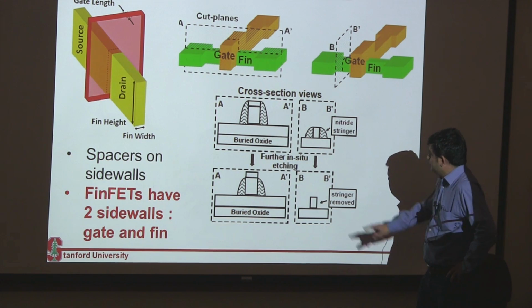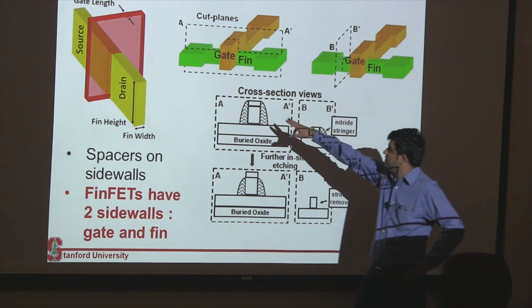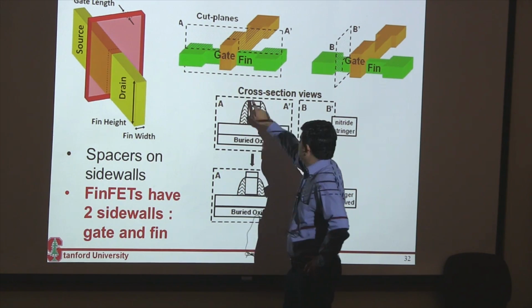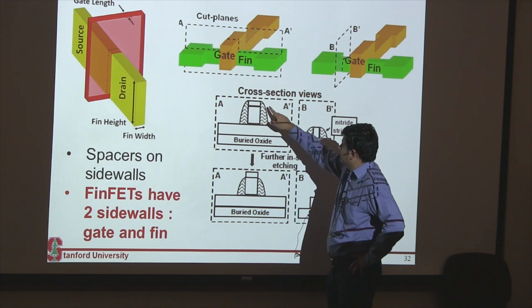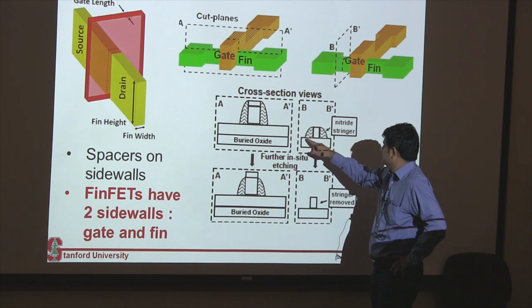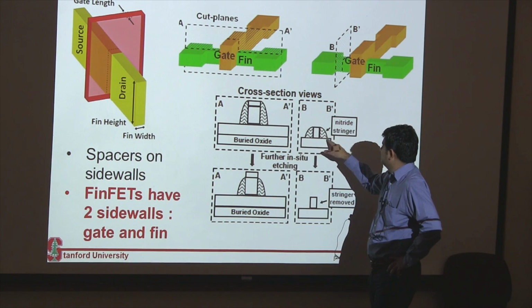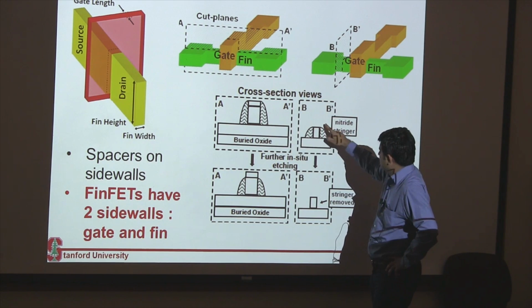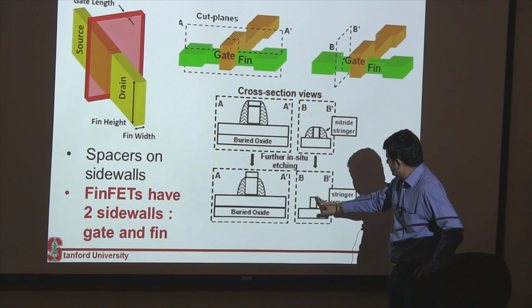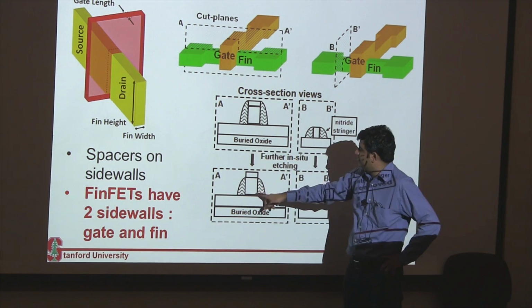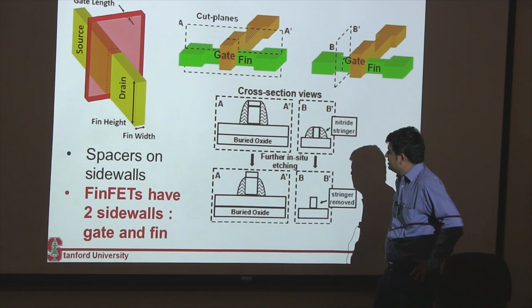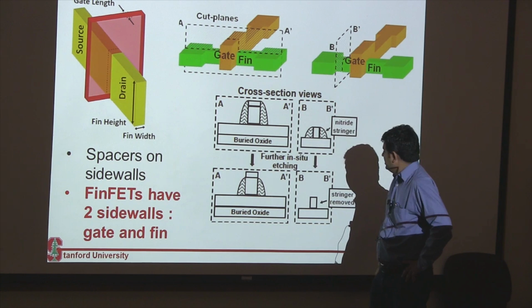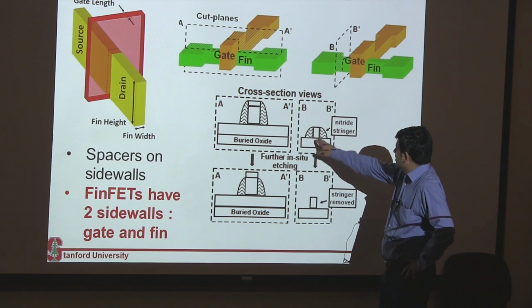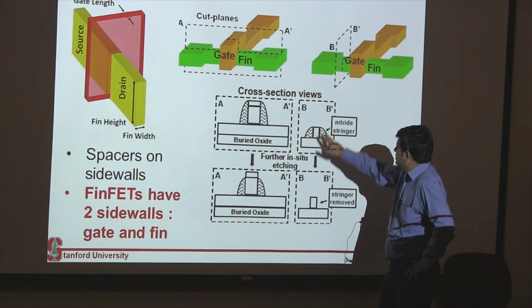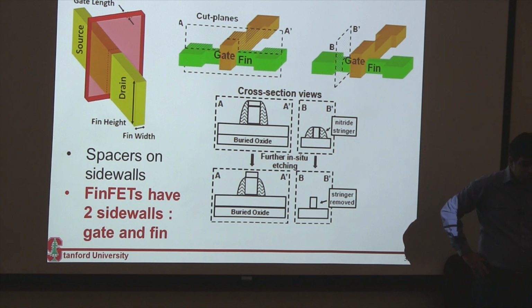my process. So what they do is, they make this gate taller, so you get a spacer which is like this over here, which is tall, and you also get this spacer which is on my fin, and then I can do a very sophisticated etch such that I etch this part out and I remove this spacer because I don't want it, but I still keep my spacer on my gate, between my gate and source drain. So again, it works against my argument that I really want to make these fins taller, but then I can't remove this stringer around them. So this is again challenge number 3.